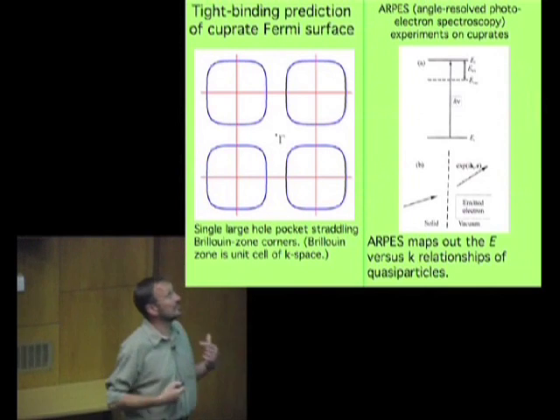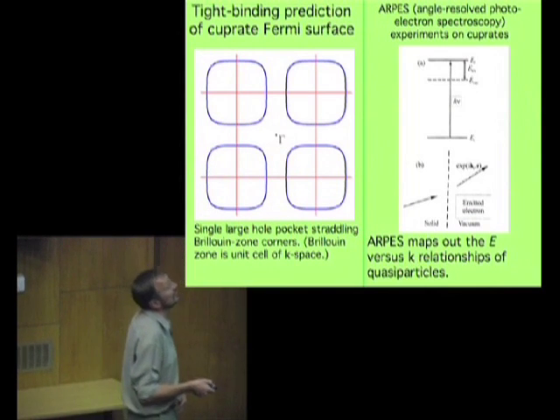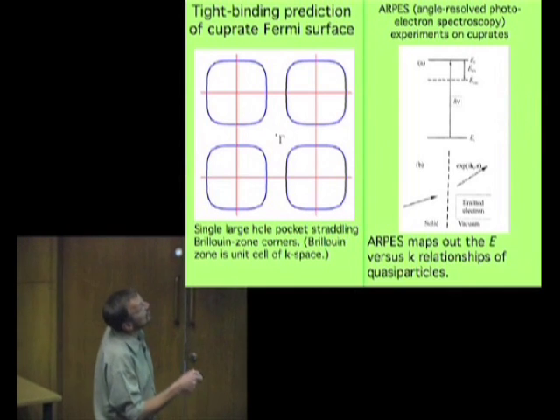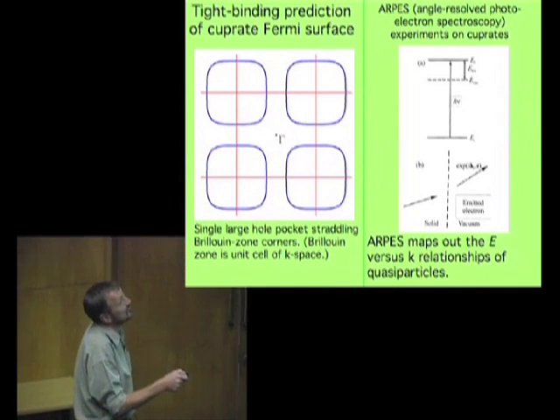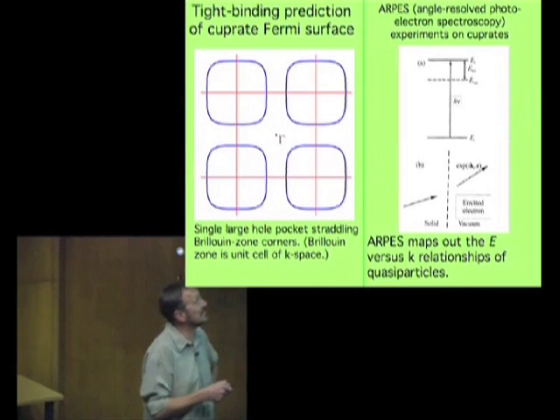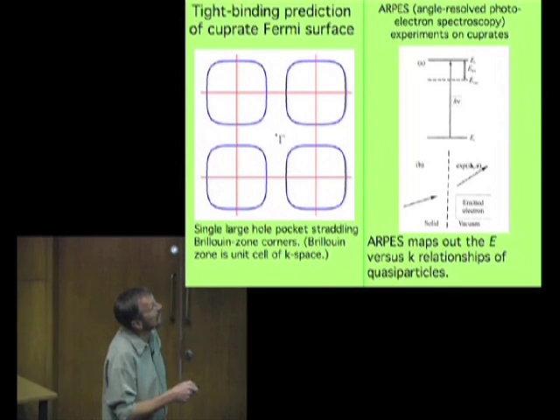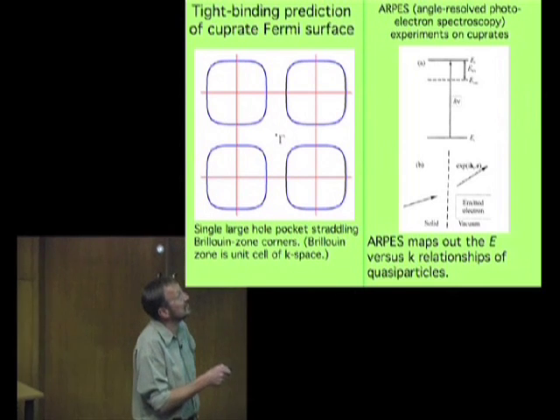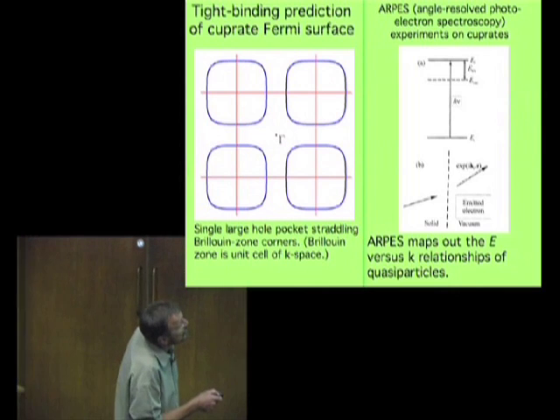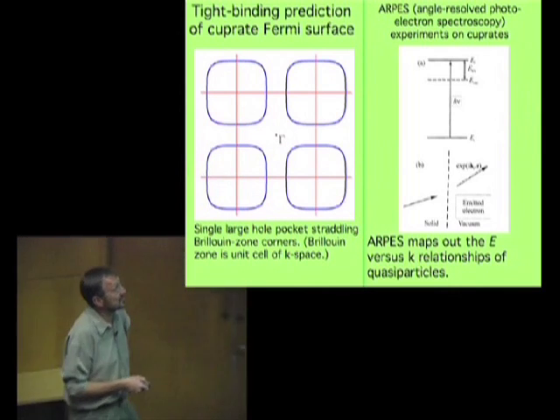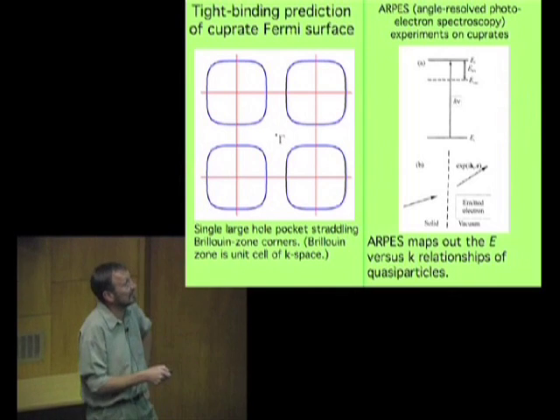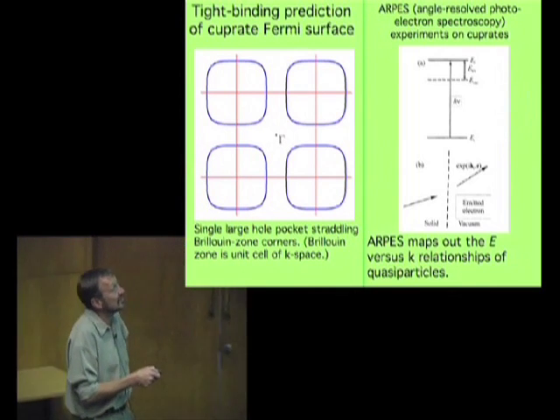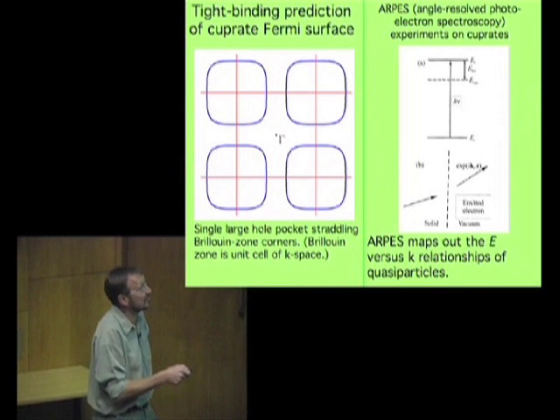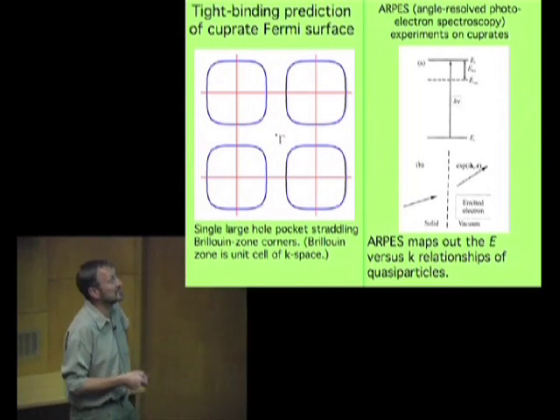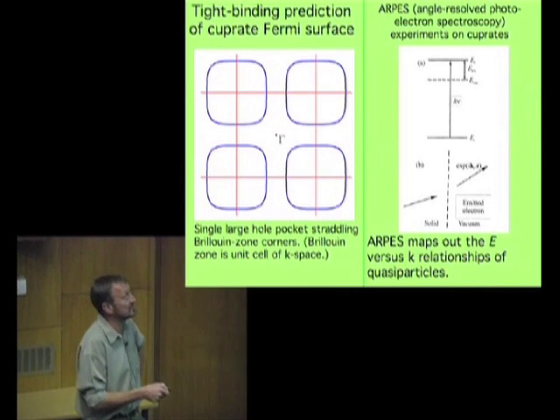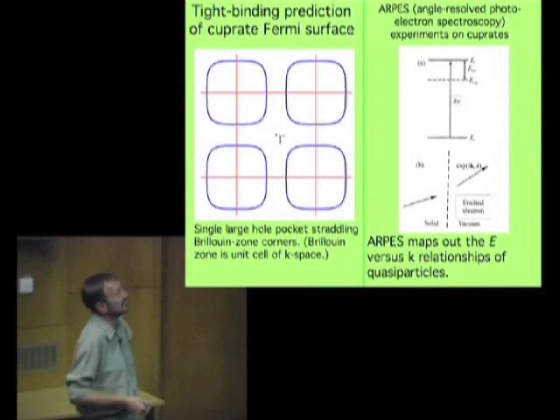So, first of all, the measurements of Fermi surface that were in the literature up to about a year ago were done by a technique called ARPES, angle resolved photoelectron spectroscopy. What this does is we take in a high energy photon, it kicks the electron up from a low energy, and then we get a recombination event which results in the electron being emitted from the solid. So we get the electron coming out from the metal, and because the states which determine the electron's emission are determined by the Fermi surface, we can use this technique to map out the energy versus K relationships of the quasiparticles and therefore measure the Fermi surface.